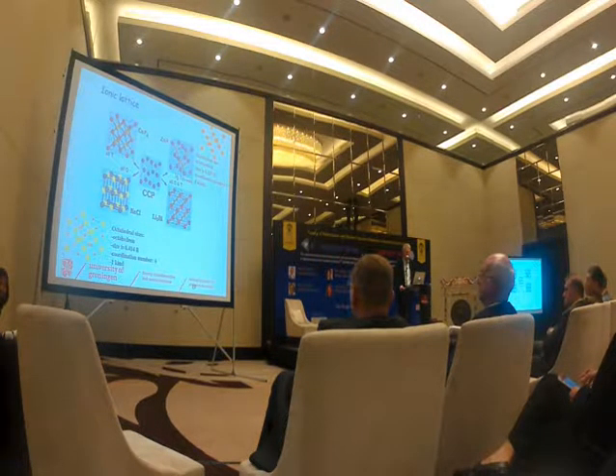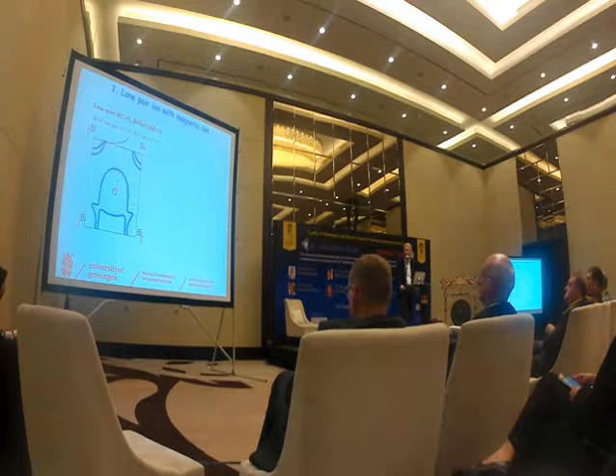Nevertheless, all of these structures are based on dense packing. Dense packing implies absence of inversion symmetry. So if you would like to have materials that lack inversion symmetry, you have to do something different. And something different is to use elements that lack inversion symmetry themselves. A good example are atoms that have a lone pair electron, like bismuth or lead, and the lone pair displaces atoms with respect to the inversion center and gives rise to polar materials.